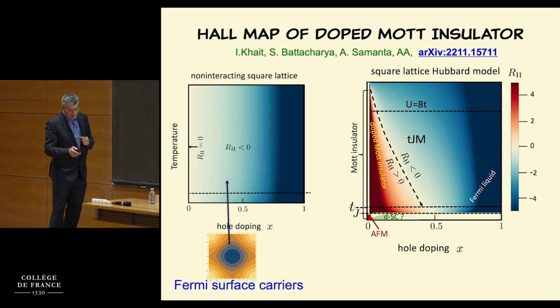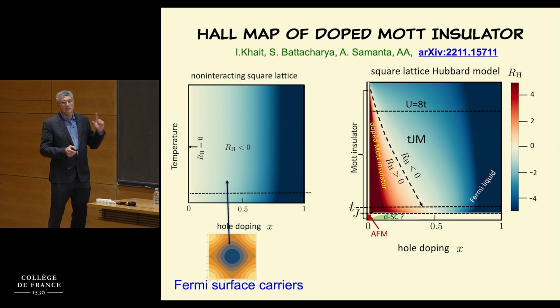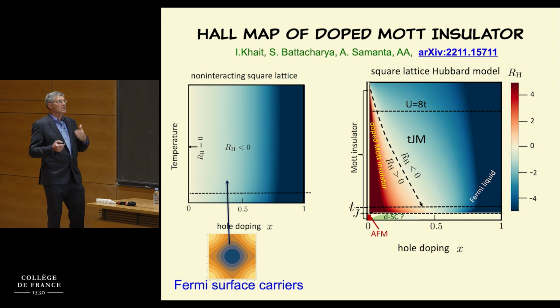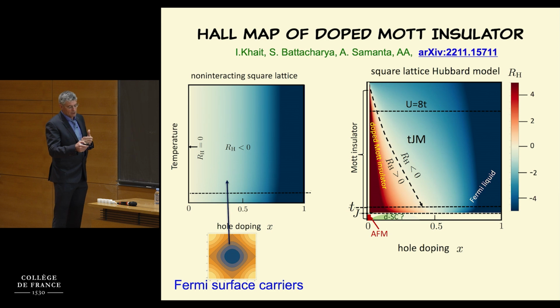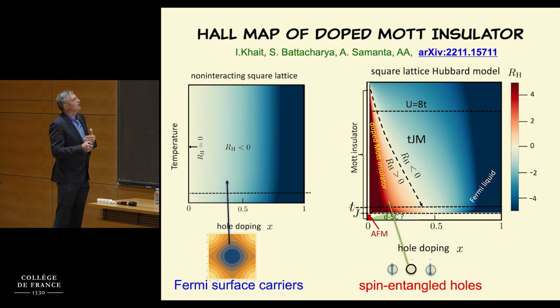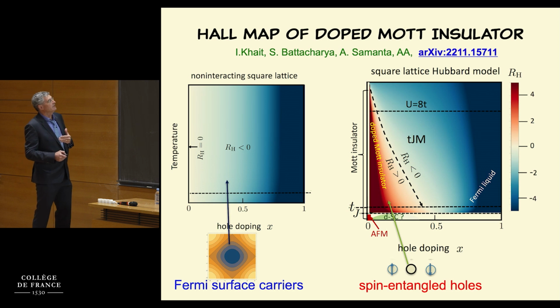This is the result. So I'm comparing my results to the non-interacting theory, the theory which has no interactions, which is the usual, or weak interactions if you want, weak scattering, which is the theory that can be applied, the Boltzmann equation and diagrammatic perturbation theory and so on. That theory will tell you, for the tight binding model with no next nearest neighbor interaction, the Hall effect is totally negative. It diverges, as we said, in the bottom of the band, and it crosses zero, that's the white area, at half filling.